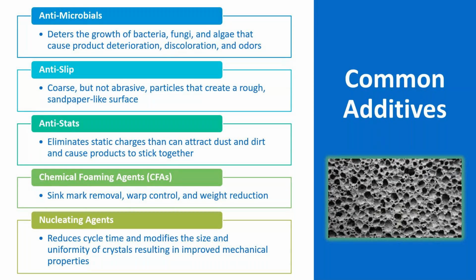Nucleating agents, some of these come inherently in some of your polypropylenes. So if you look at some of the polypropylenes out there, they'll come nucleated and anti-stat already. It's pretty common for them to do that. But your nucleating agents will help reduce your cycle time. It makes areas for the crystallization to start happening and happen quickly, and then it happens more uniformly because of those site locations for it to start to occur.